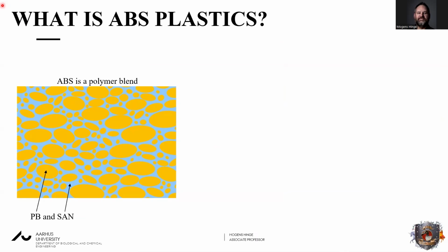So if we zoom in onto the material, then we'll see that ABS is not a homogeneous polymer, but it is a polymer blend. So that basically means that we have a base matrix here illustrated in light blue. And in the case here, it is a styrene acrylonitrile base that we have. And then in this base, we have islands or small lumps of polybutadiene. The polybutadiene works in a way that when you impact, for example, the ABS from below here, then the SAN phase here will deform and then transfer the energy into the polybutadiene phase that will deform and convert the energy into heat. So in that way, the material does not shatter or break when it is subjected to an impact, but it simply takes all the forces and diverts them into the material, and then in each of these small lumps of polybutadiene, they will then convert it into heat.